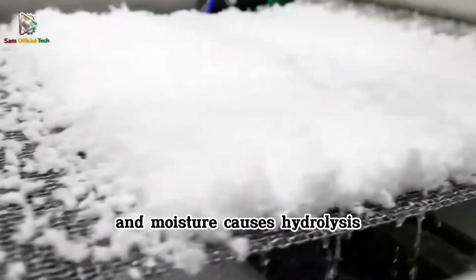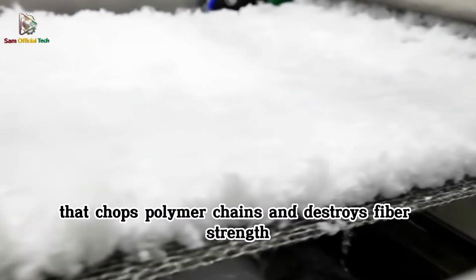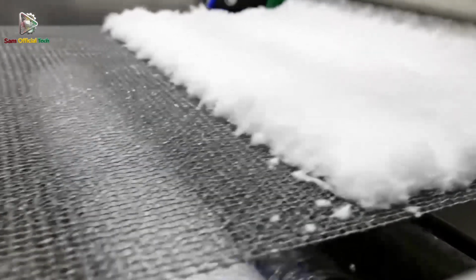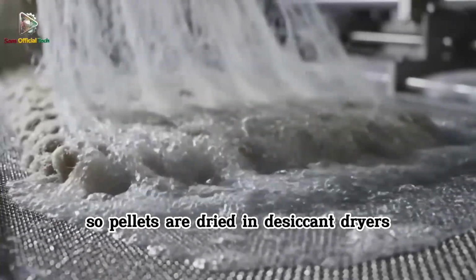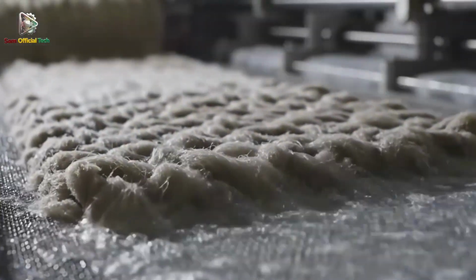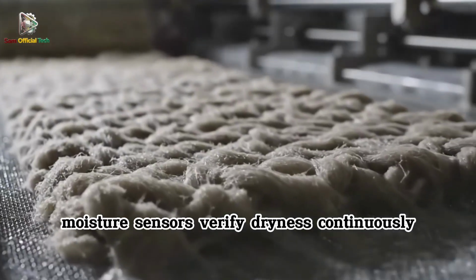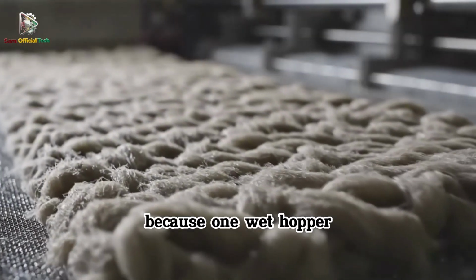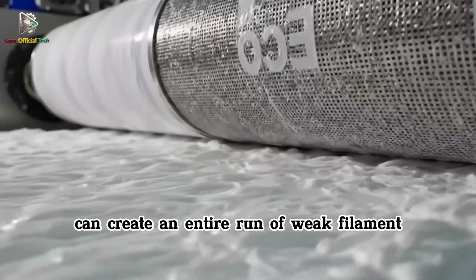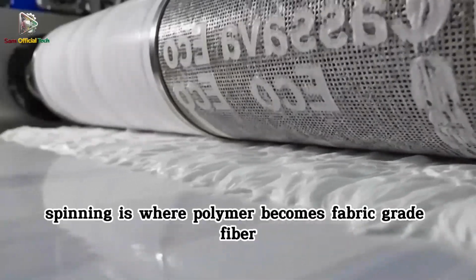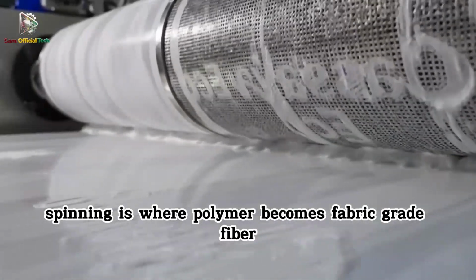And moisture causes hydrolysis that chops polymer chains and destroys fiber strength. So pellets are dried in desiccant dryers to very low dew points. Moisture sensors verify dryness continuously, because one wet hopper can create an entire run of weak filament. Spinning is where polymer becomes fabric-grade fiber.